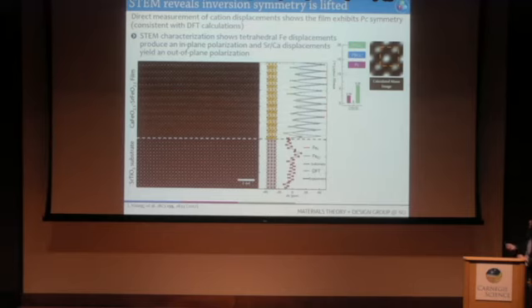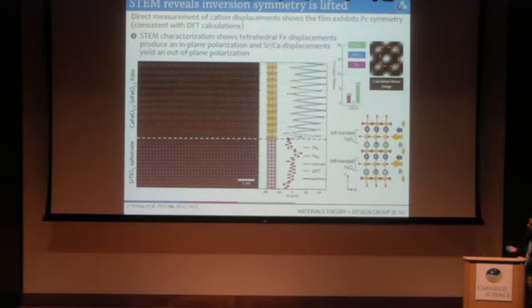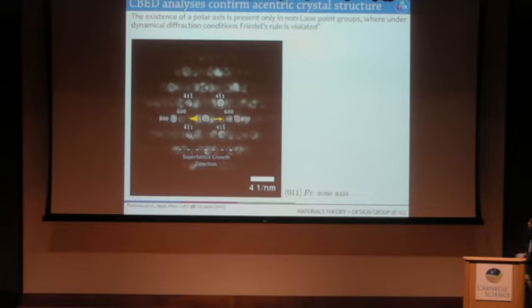And in fact, the structure is predicted to have the Pc symmetry, so not the one we predicted to be the ground state, but one very close in energy with that phase. And so what they looked at and imaged, and could plot and track, is the displacements of these iron units in the superlattice. And the last thing that I'll show you is that they did indeed confirm the broken inversion symmetry using a CBED technique, so an electron microscopy technique, where they looked for asymmetries or violations of Friedel's rule in the disks that should correspond to the same types of intensities.